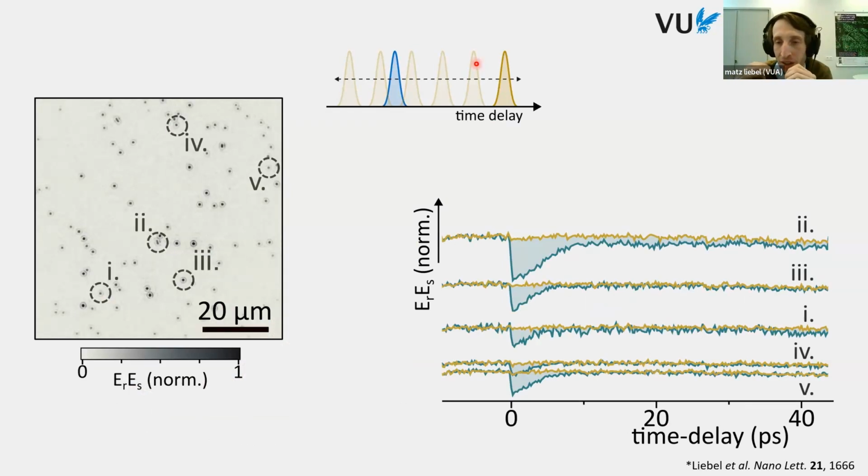One is that it might be difficult to see minor oscillations. The other one is that this modality really relies, at least for these particles, on the hot electron contribution where we get a massive signal change due to the plasmon resonance shift. Also the plasmon enhances these oscillations; they are visible because of the plasmon. Yes, without plasmon you couldn't see them.